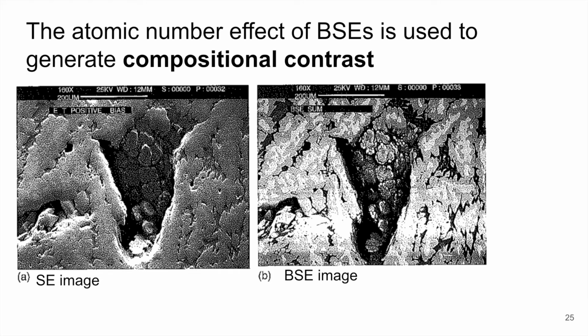But hidden in that, if you look at the backscattered electron image, this region right here, if you look at it closely, there are regions that are lighter and regions that are darker, right? So on that single piece, we actually have differences in contrast, and that's the different phases that we see. That's the additional information that you get here that you don't get on the secondary electron image, because it's not giving you that difference from atomic number.